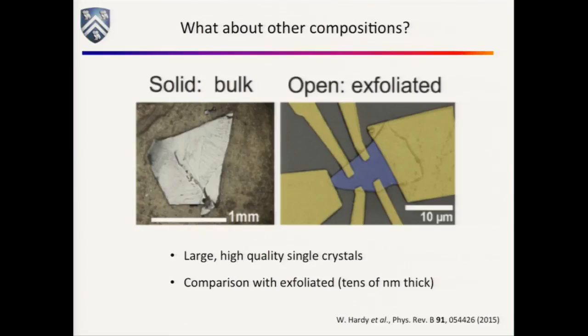What you find is you can grow stuff at different compositions. You can vary the amount of iron inside the material. And so here's a big bulk crystal. Here's an exfoliated piece that's actually not very thin. We had a really tough time getting this stuff very thin. The iron makes the layers really want to stick together. So this is tens of nanometers thick, which is why it looks so bright in this micrograph.